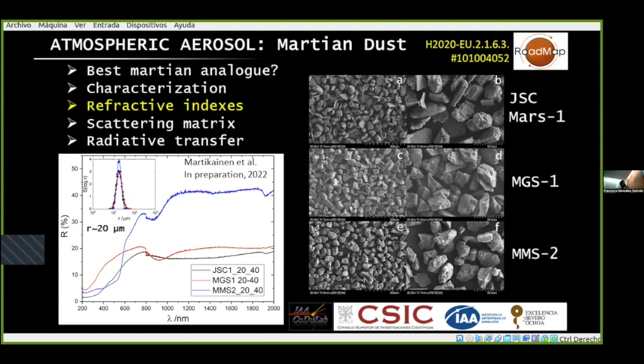So what we have done is to take all the Martian analogs available in the market, because this is actually a market, they are sold. And then they've been sent to the Institute of Glass and Ceramics to select them in different size distributions. They have fantastic capabilities for doing that. And actually the size distributions that we get here and the ones we use in the lab are unprecedented in our field, in the sense that they are extremely narrow. So, I mean, you cannot consider them as monodispersed, but they are very, very narrow. That gives you the opportunity to at least understand what is the effect of size if you have very different, non-overlapping distributions and you do the measurements of the scattering properties.